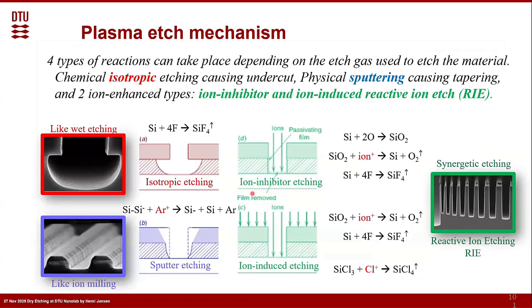Now, 4 types of reactions can take place during etching, depending on the etch gas used to etch the material. It is chemical isotropic etching, which is causing undercut, physical sputtering, causing tapering, and 2 ion-enhanced types, so the ion inhibitor and ion-induced reactive ion etching.